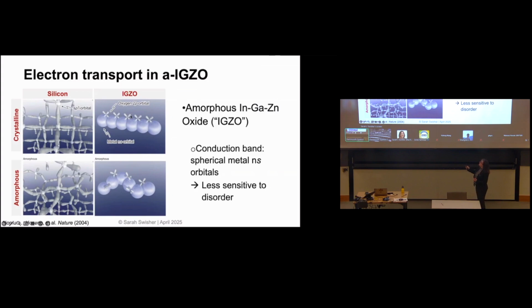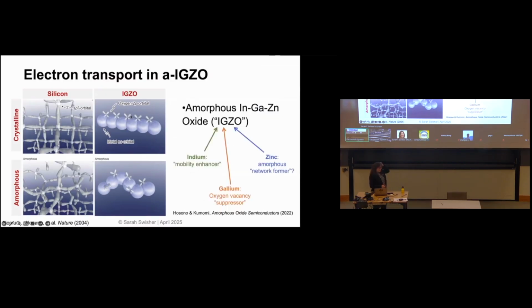This is what those orbitals look like for this oxide semiconductor. Notice that instead of having this shape that looks like a tetrapod that has those legs like a jack, it's a big fat sphere. Spheres overlap really nicely. So this is what has made this material so unique and so exciting for many of us who are in thin film devices, because if they're nice and orderly, great. Those spheres overlap, the electrons can run through that. But even if you change the orientation, it doesn't matter. You can still get the electrons through. So this orbital overlap in these large spherical orbitals is what gives these devices such a unique transport property.